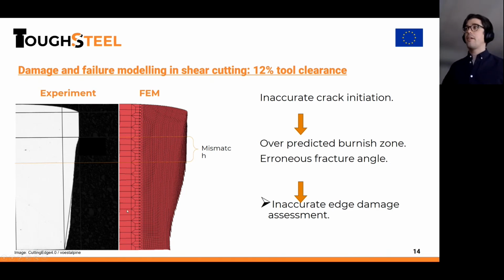Here you see in red a finite element mesh of a cut edge next to an experimental cross section of a cut edge for the same tool clearance. We see that the rollover seems fine, which means that we have okay plasticity and our compressive shear failure modeling is on point. But the shear zone is too long in the finite element model, which means that the crack initiation after the shearing is inaccurate. And in the end, this gives an inaccurate cut edge shape with wrong fracture angle and a wholly inaccurate cut edge damage assessment. This is a clear example that without treating cracks in a proper way in modeling, you might end up with not so good results.